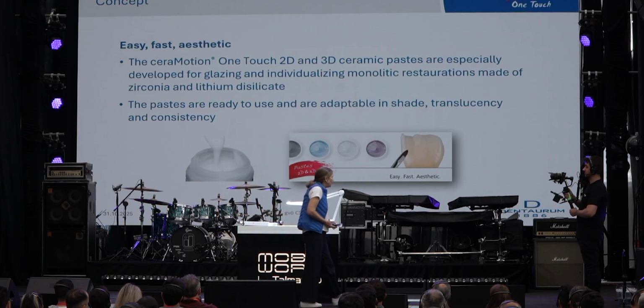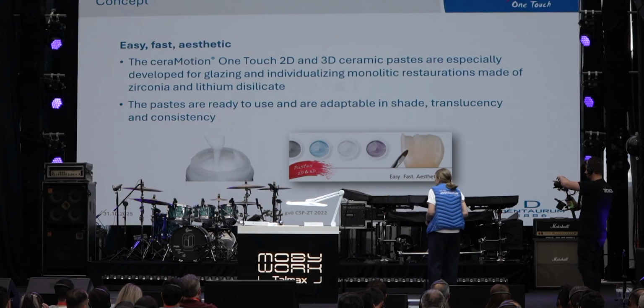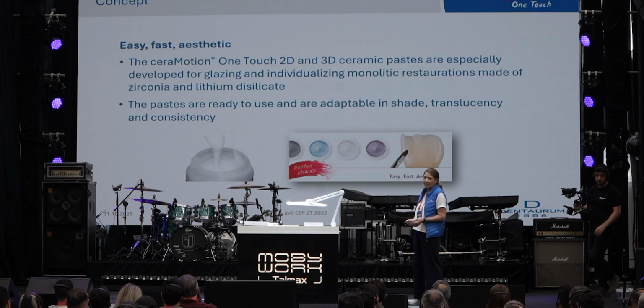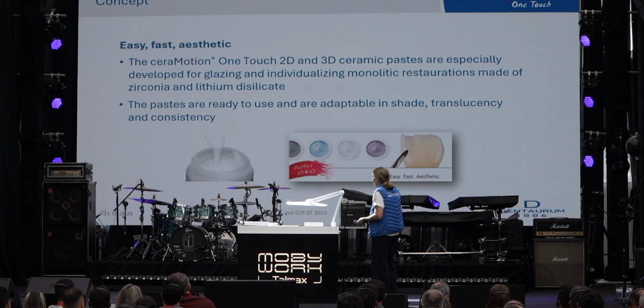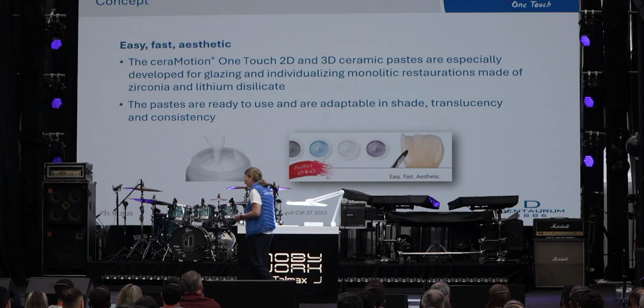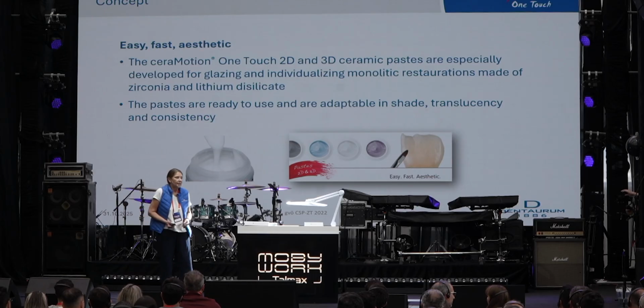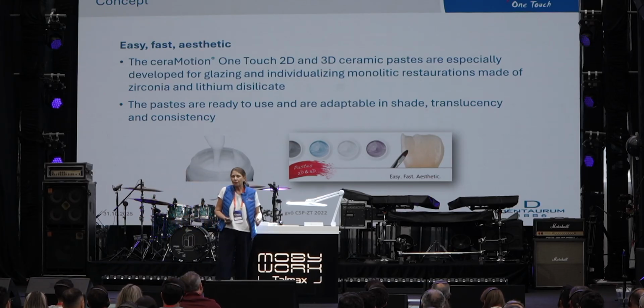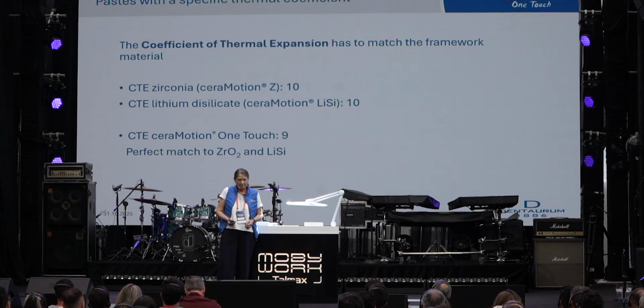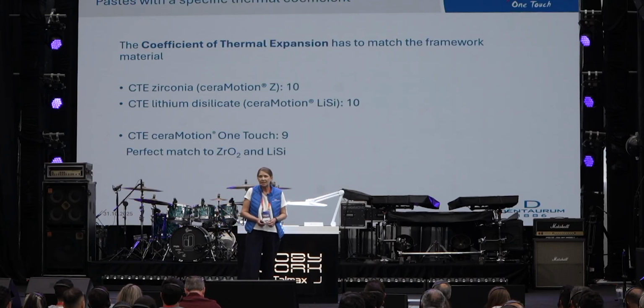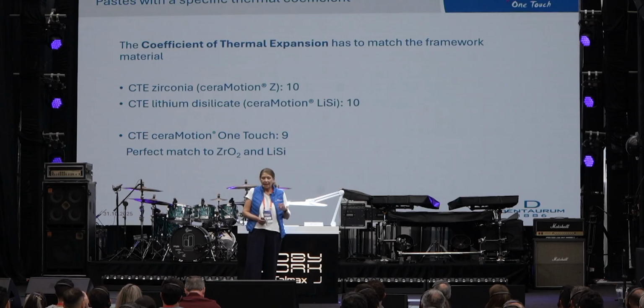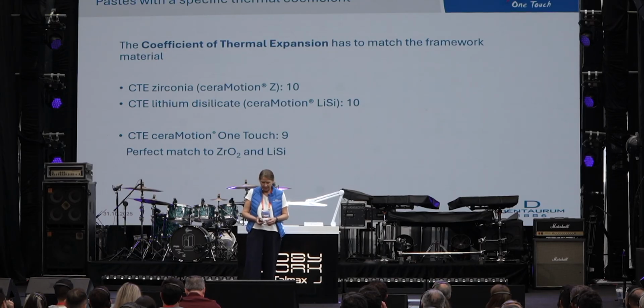So that's how we created the CeraMotion One Touch. CeraMotion One Touch consists of 2D and 3D pastes. They are developed especially for the monolithic field, and the pastes are ready to use, but of course you can also adjust them with some liquids. Very important for us was the CTE. The CTE must fit the framework. If the CTE is too high, it's not a match. If it's too low, it's not a match. And especially for the 3D pastes, the CTE must fit the zirconia as well as the lithium disilicate.